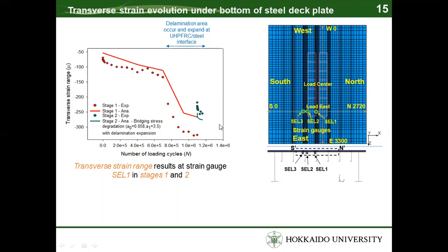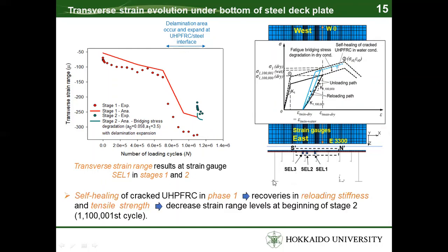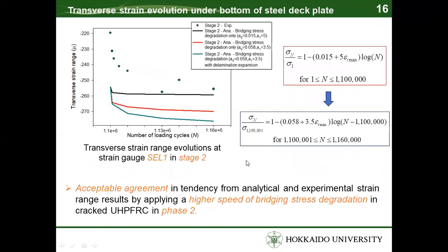And after that, in stage 2, under surface water conditions, due to the recovery in reloading stiffness and tensile strength caused by the self-healing of cracked UHPFRC, a decrease in strain range level could be observed from the beginning of this stage. And after that, under moving wheel loading, due to the fatigue life reductions of UHPFRC, an increase in transverse strain range level could be obtained. In phase 2 of material model, by applying the higher speed of bridging stress degradation in cracked UHPFRC, an acceptable increasing tendency in the analytical and experimental strain range results could be obtained, especially for the early cycles of this stage.